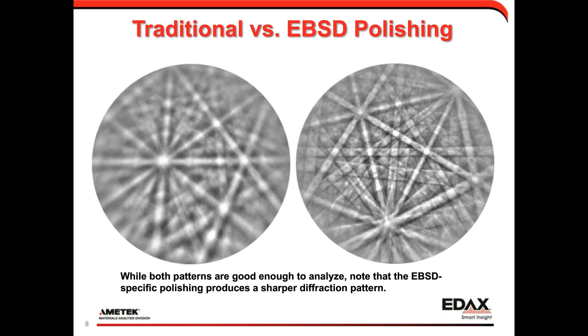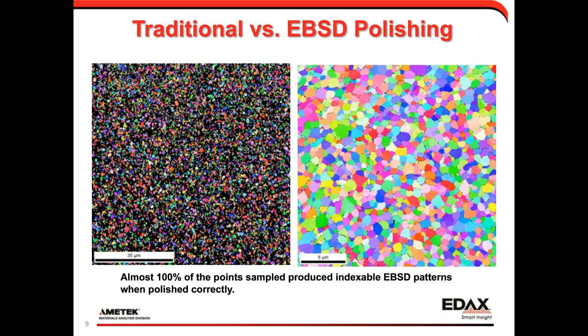And this compares the actual map on the left, where we get a lower indexing rate, with the map on the right with EBSD polishing, where we get nearly 100% of the points correctly indexed. So clearly, if we prepare a sample with EBSD in mind, we can improve the quality of our final results and get a more accurate representation of the material microstructure.